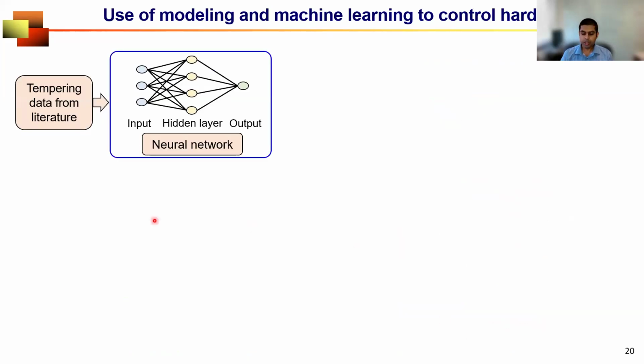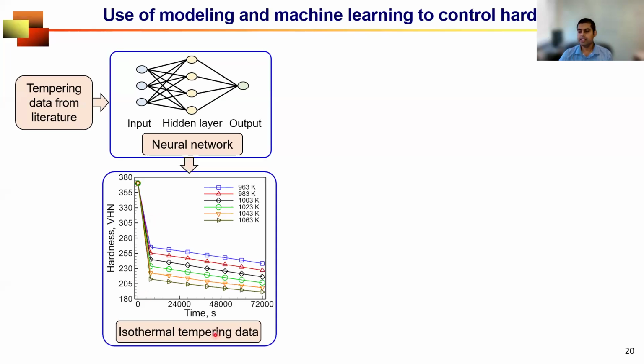What we did, we used the isothermal aging data. Now, for a complex material system like grade 91, it's very difficult to get reliable data on isothermal aging. So what we did, we collected a lot of data from the literature and then used those data to train a neural network, and then used that neural network to generate a lot of tempering data for different time and temperature combinations. Once we have that, we get the constants in the Johnson-Mehl-Avrami equation. What's this equation? If you don't know, it's a very famous equation for capturing isothermal phase transformation.